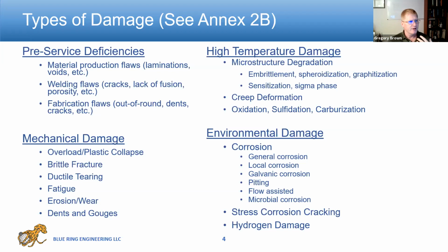You could have high temperature damage. This is when you operate equipment at too high of a temperature, you can get creep damage, as it's called. Creep damage is where you're actually creating voids in the structure. This eventually leads to cracking and eventual failure. It requires time, temperature, and stress for that to occur. You can have environmental damage. Most common environmental damage we encounter is corrosion, of course, where we have metal loss that reduces our wall. Can we still hold our pressure?